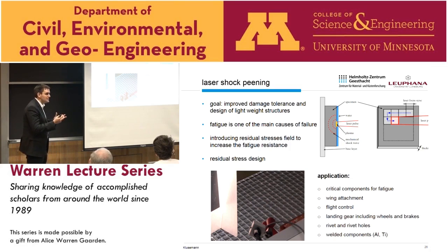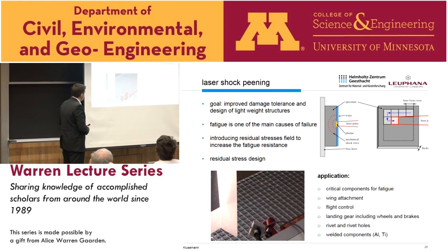So why do we do that? Well, fatigue is one of the main causes of failure mechanism. And when we have a residual stress field, compressive residual stresses, this increases the fatigue resistance. So we need a specific residual stress design. So here on the bottom, you can see now our process in the simulation, hopefully.